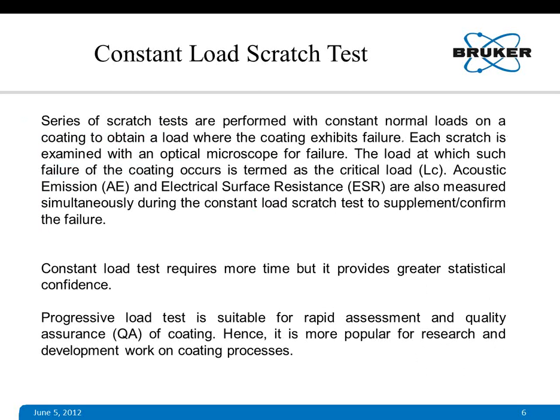On the other hand, the constant load scratch test is done, as it implies, with a constant load. The load remains constant and you scratch at different load levels. A series of scratch tests is performed with constant normal loads each time, but the level may be different, till the point where failure of the coating occurs. Each scratch is examined with an optical microscope for failure. Sometimes the tangential force, Fx, or other parameters such as acoustic emission or electrical contact resistance also exhibit sudden changes at the point of failure. They can also be used to pinpoint at what point failure is occurring. The load at which such failure of the coating occurs is termed the critical load again.